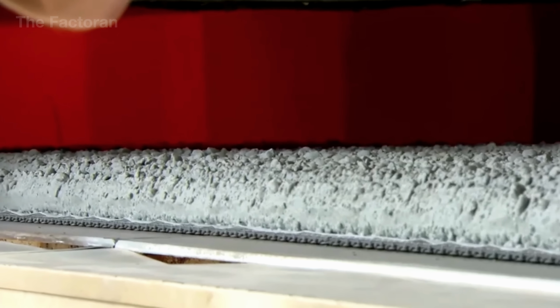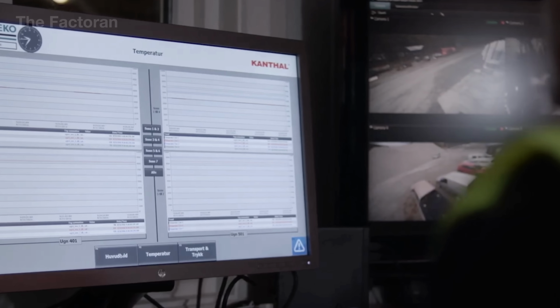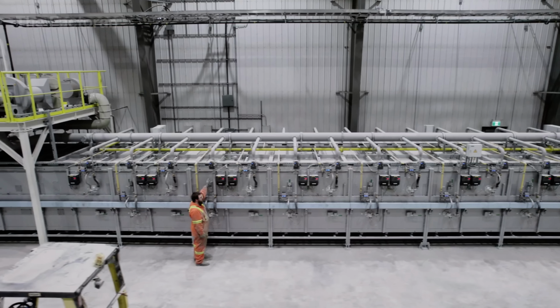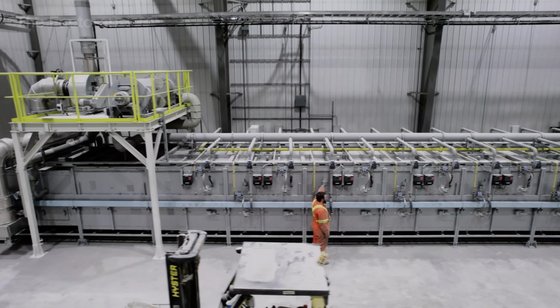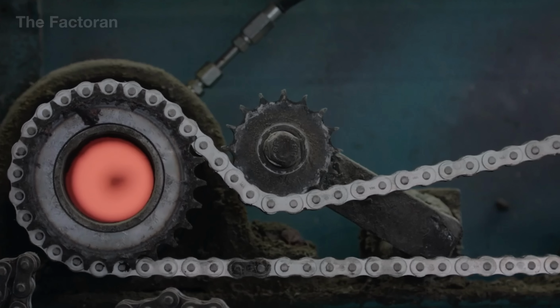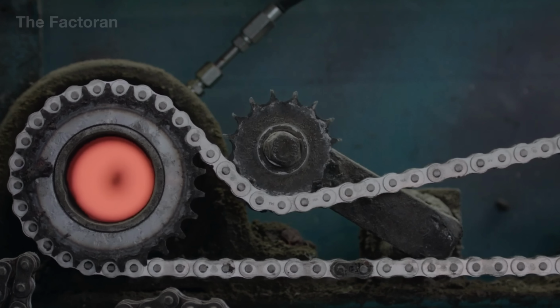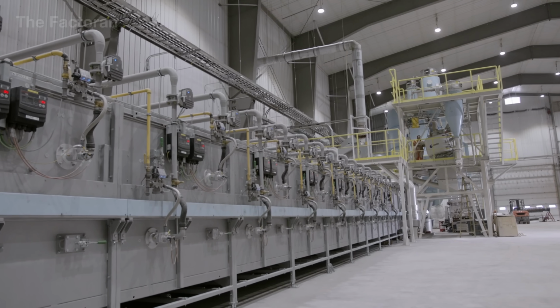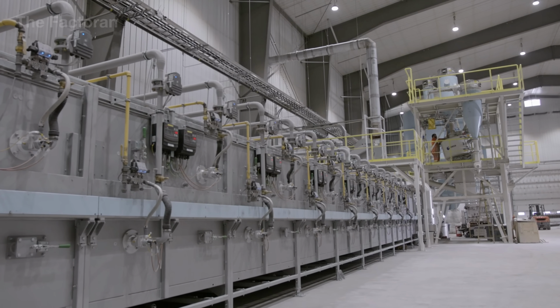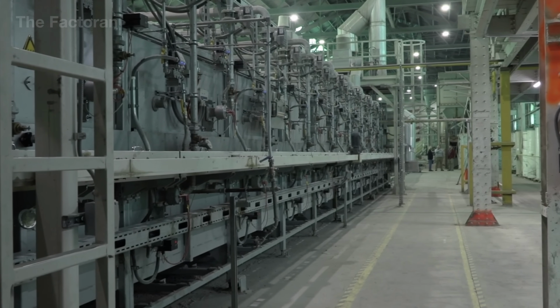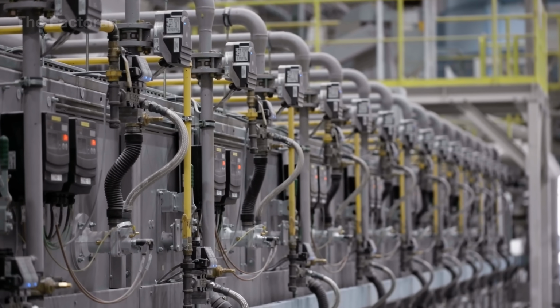The heating rate is controlled with extreme precision. If it increases too quickly, the gas escapes before the glass becomes pliable enough to retain the bubbles. If too slowly, the foam structure collapses, increasing density and reducing insulation performance. For this reason, foam glass production lines use zone furnaces where each section operates at a specific temperature and residence time, typically totaling 45 to 60 minutes for the entire cycle.